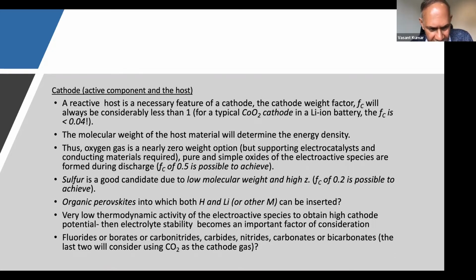So what we're looking for here is a very low thermodynamic activity of the electroactive species to obtain a high cathode potential. And at those kinds of potentials, electrolyte can readily be decomposed. So therefore, a search for a proper electrolyte becomes a very important part of the research. And there are other opportunities that may use CO2 as the cathode gas instead of air. So therefore, I can start using some of the CO2 that we produce as actually a material for generating energy.